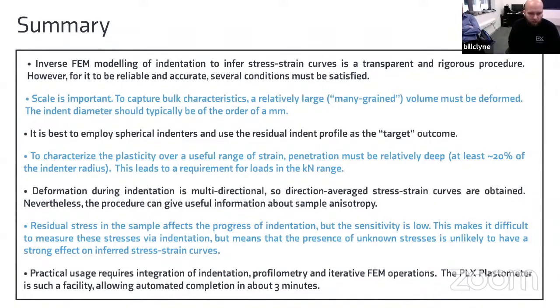So we then had a look at anisotropy, noting that indentation is multi-directional, so we get a direction averaged response. And we looked at the case of a nickel-based superalloy. Residual stress can affect the process, but the sensitivity is low. This is especially true for larger penetrations, although it can have some effect at lower penetrations.